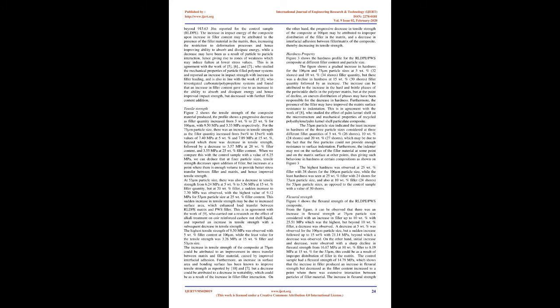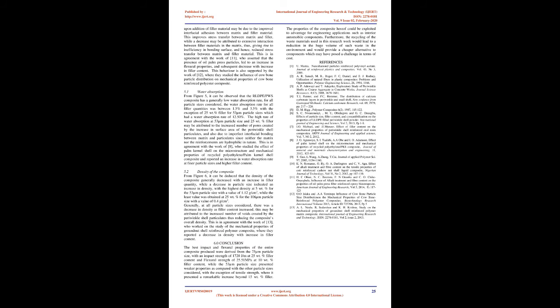A decrease at 5 weight% was observed for the 106 µm particle size, but a sudden increase followed up to 15 wt% with 21.14 MPa, beyond which a decrease was observed. On the other hand, initial increase and decrease were observed with a sharp decline in flexural strength from 16.67 MPa at 10 weight% filler to 8.19 MPa at 15 weight% for the 53 µm. This could be as a result of improper distribution of filler in the matrix.